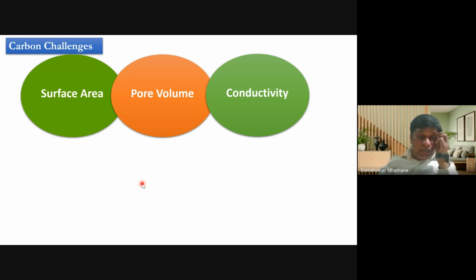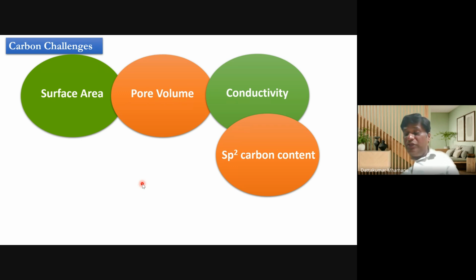Then conductivity. If you talk about chemically prepared graphene, in graphene preparation we have to introduce oxygen first, which is called oxidation of graphite. Once we get graphite oxide, we have to remove that oxygen, and then we get only graphene. But chemically it is not possible to remove all the oxygen. Once the oxygen is inserted inside the graphite layered structure, in graphite oxide, it loses its conductivity. After reduction, it regains conductivity, but the oxygen-containing groups are not completely removed, and because of that, the resulting graphene is not that conductive. So people have to find a new reducing agent in order to get good conductivity of that graphene.